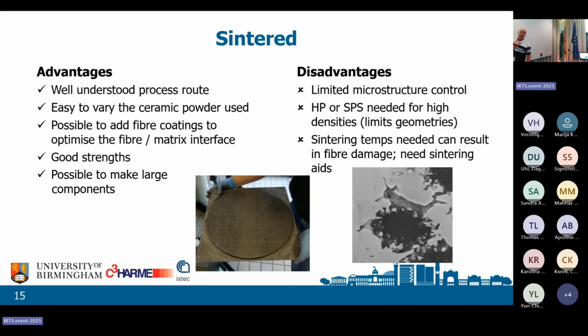But you have got limited microstructural control. You do need pressing. That limits the geometries you can form, and the sintering temperatures, even with hot pressing, 1800, 1900, carbon fibers really don't like that. That's what's left of a carbon fiber after being pressed. So the carbon fibers really don't like it. That means you need sintering aids. That just makes it all the more complicated, but never forget it works. That's a crucial thing.